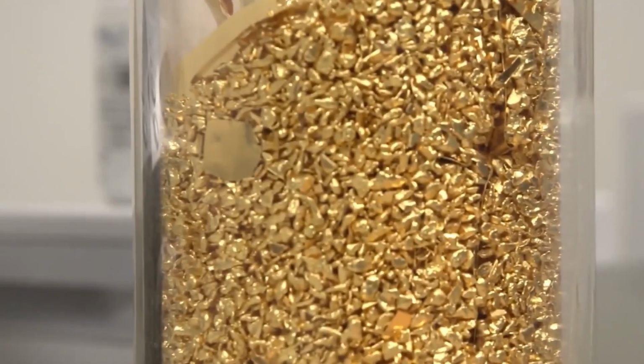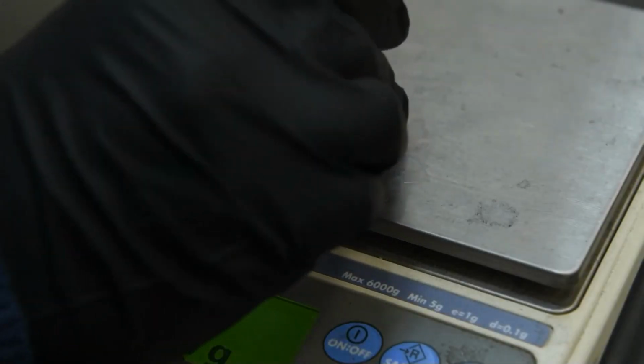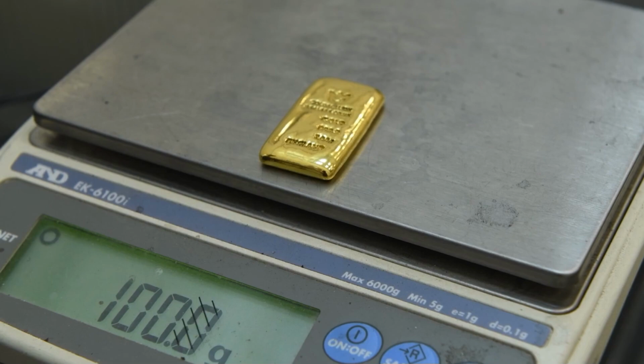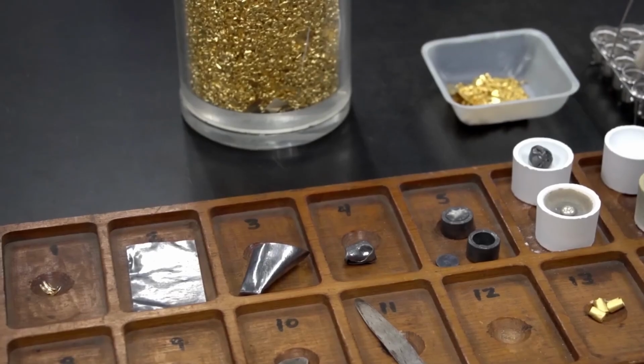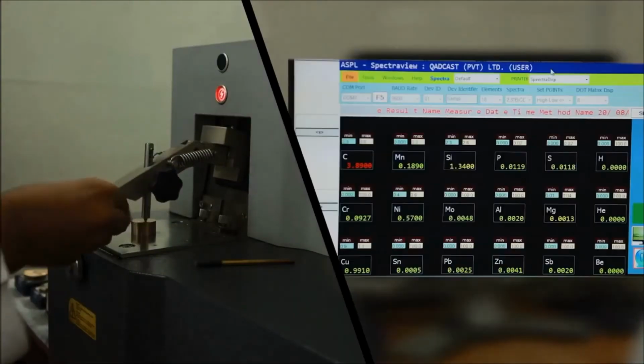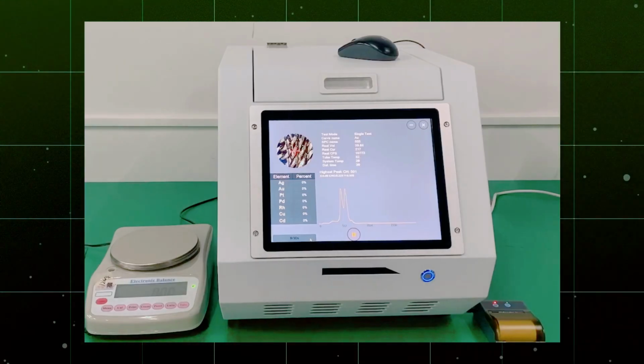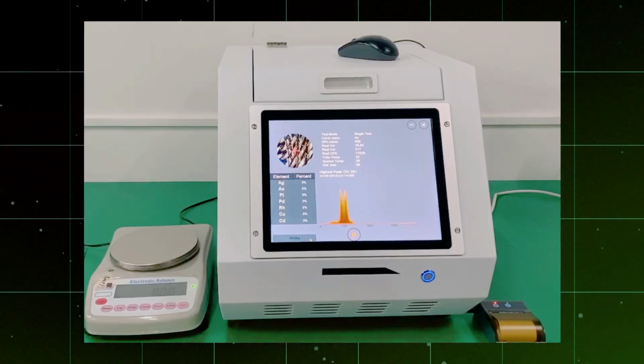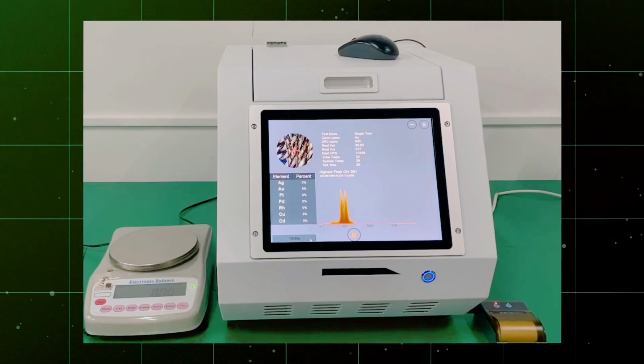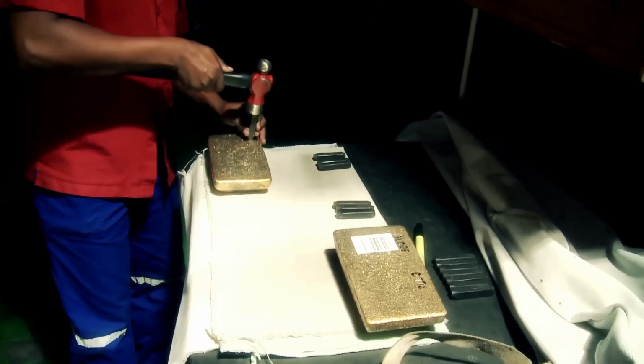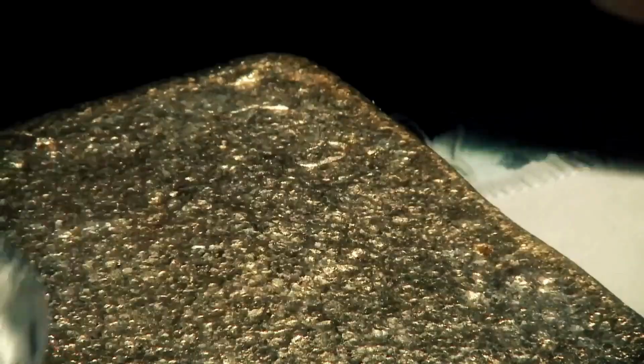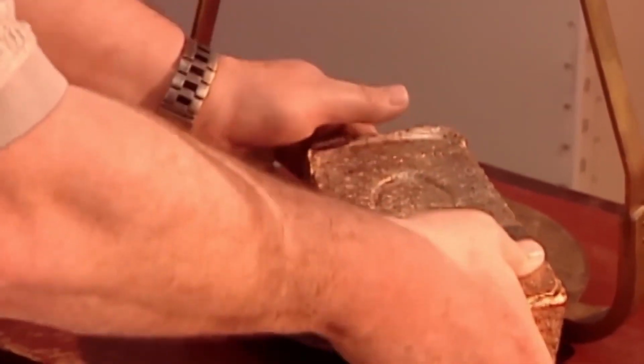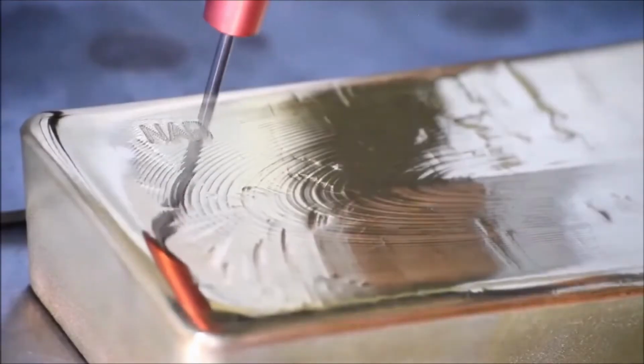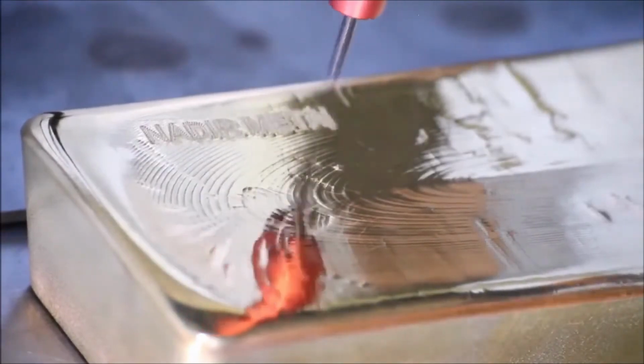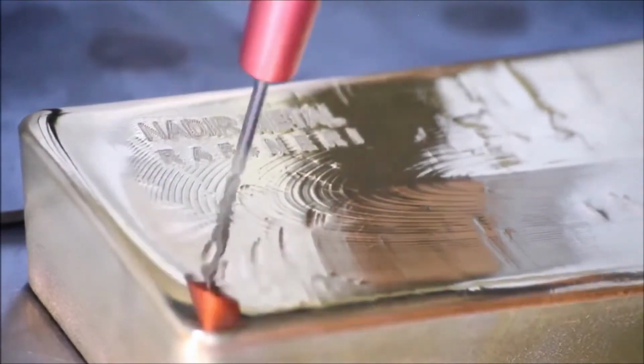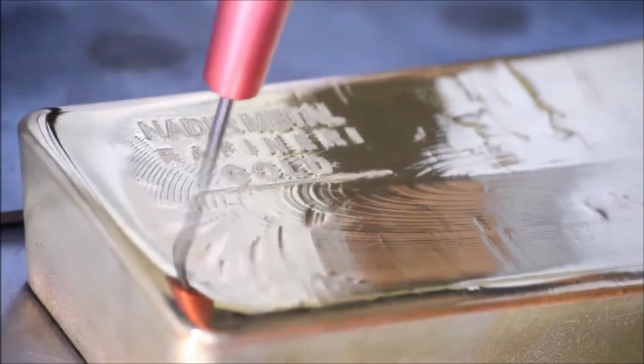After the gold bars have completely cooled and been removed from the molds, they undergo a rigorous inspection process. This step is essential to ensure that each bar meets the international standards for purity and weight established by the industry. The inspection includes both visual assessments and advanced tests, such as spectrometry, to confirm the gold content and ensure the bar has no defects, porosities, or residual impurities. Quality control may also involve weighing the bar, which must precisely match specified standards, such as 1 kilogram bars or 400 troy ounces.